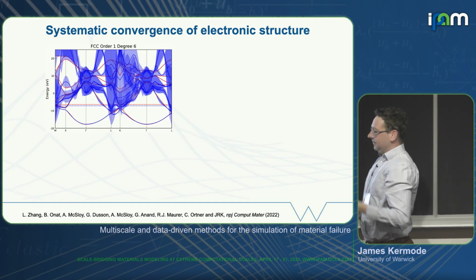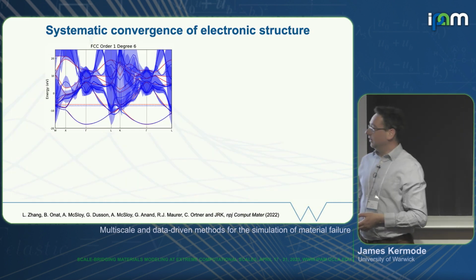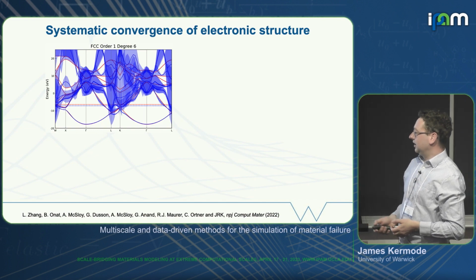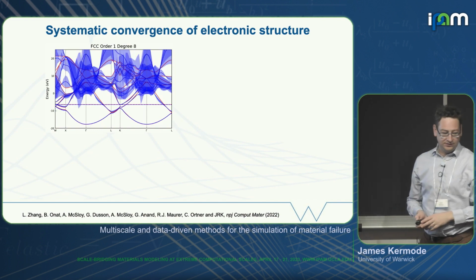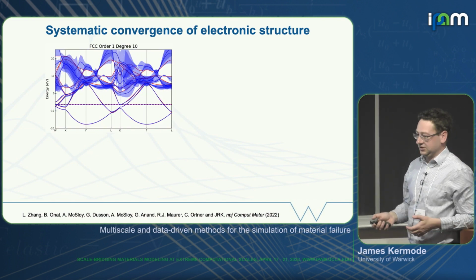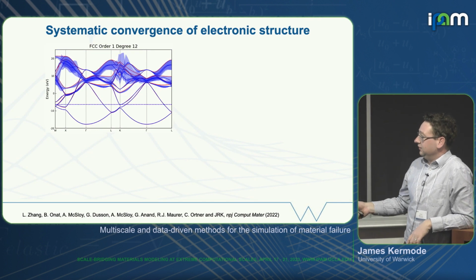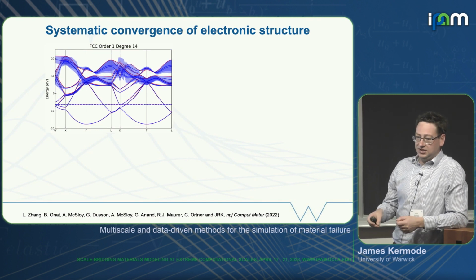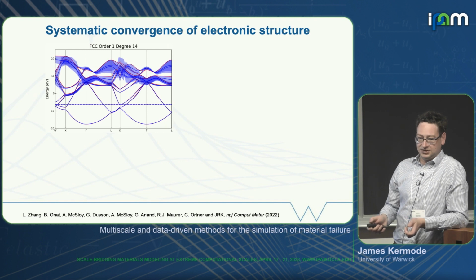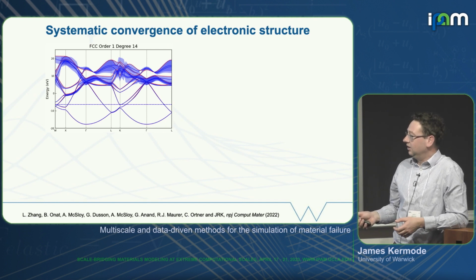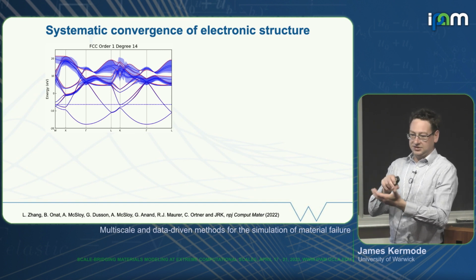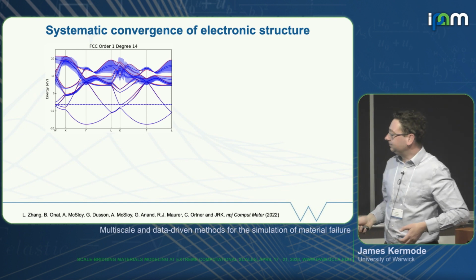If we propagate those Hamiltonians through and use them to compute band structures, they actually look pretty nice, and they improve systematically as we increase the size of the basis. So this is a band structure for FCC aluminium. We didn't include the crystal ground states for FCC or BCC in the training database, so this is a bit of a test of transferability. We only included MD data, so where the atoms were away from equilibrium.